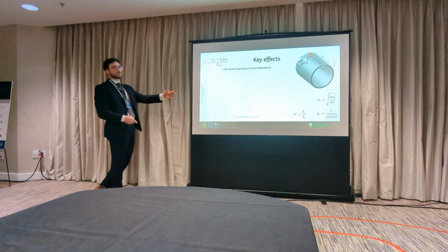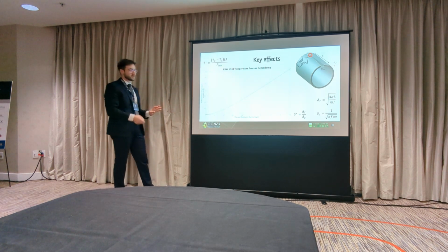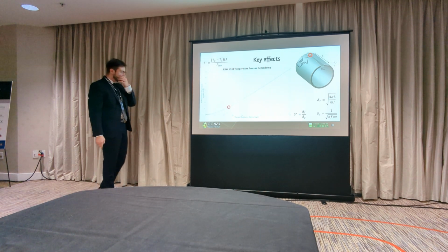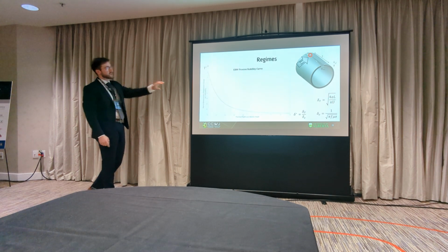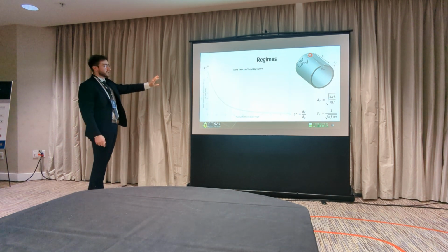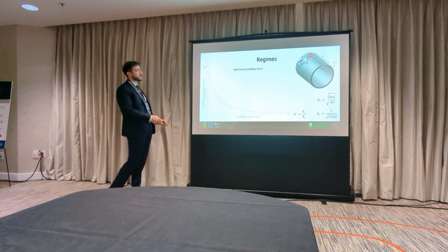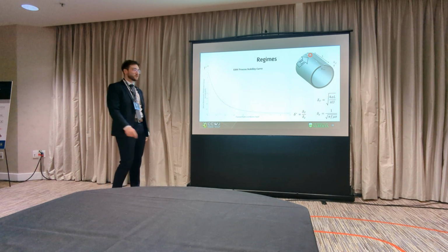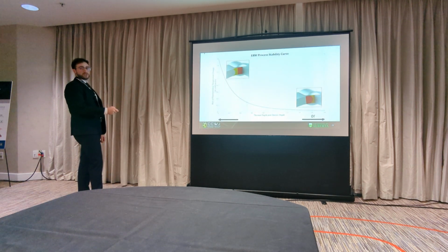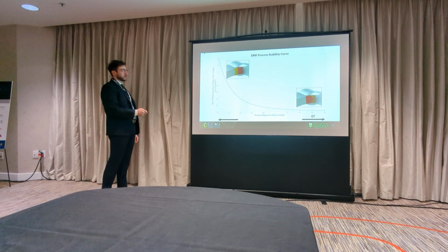This leads to the thought of a transition point and the two different regimes in the process based on this dimensionless group. And this transition point can be explored further. So this is a process stability curve. What does this represent? Again, these numbers are meaningless, but it's the shape of the curve, or the relative magnitude of the numbers that are meaningful in this case. So if we look at this, when we're in the electric regime, our delta star, our thermal depth over electric depth, is going to be small, because we're dividing thermal over electric. Because it's really small, our process stability is very low. Or instability is very high.